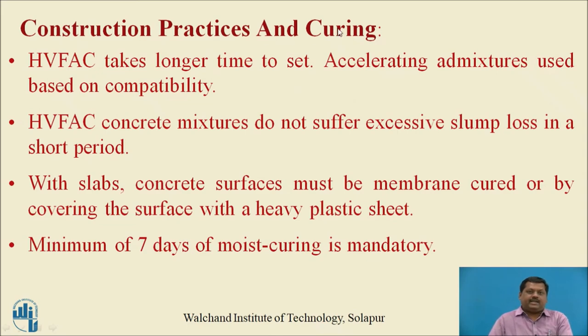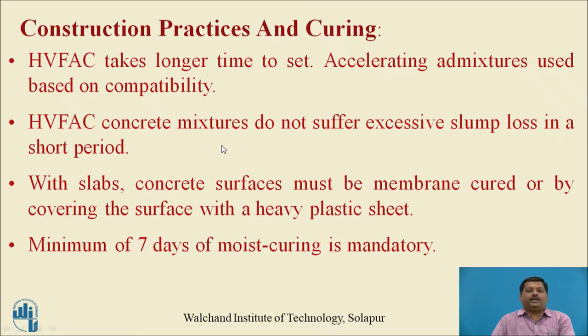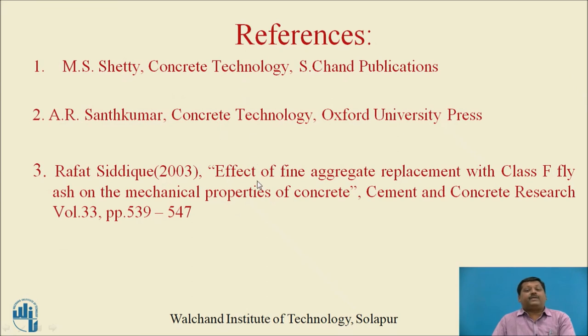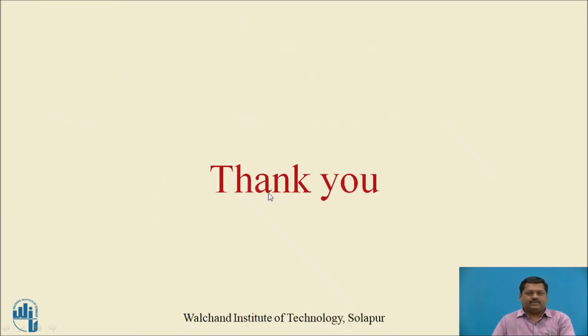Regarding construction practices and curing, high volume fly ash concrete takes longer time to set, so accelerating admixtures are used based on compatibility. These concrete mixtures do not suffer excessive slump loss in a short period. For slabs, concrete surfaces must be membrane cured or covered with a heavy plastic sheet. A minimum of seven days of moist curing is mandatory in the case of high volume fly ash concrete.